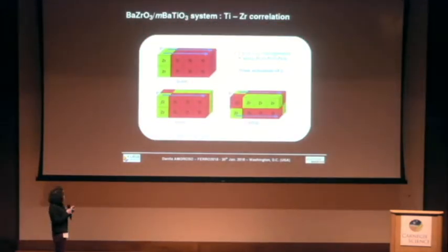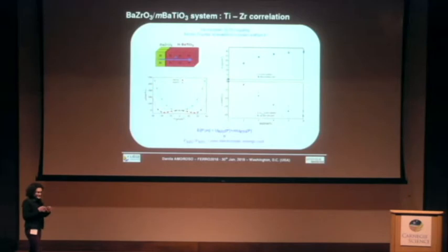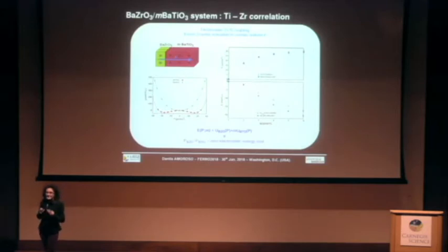Along this specific configuration, where we have one zirconium followed by several unit cells of barium titanate, the system developed a homogeneous polarization all along the chain by making the zirconium atom polar active. And the explanation of this is quite straightforward, because it's the electrostatic coupling that makes this activation of zirconium possible.